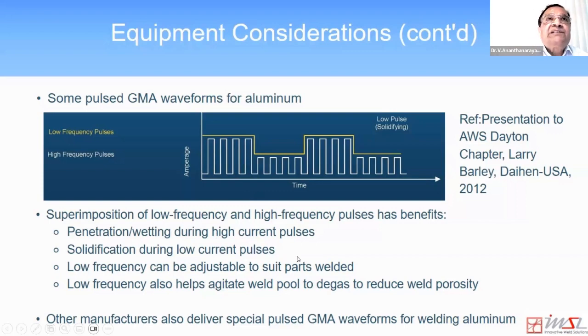One of the reasons is that aluminum is a very conducting metal. And if you keep welding at a current that melts the initial start of the weld, by the time you travel a certain distance, the weld and the metal get too hot. And there is a need to cycle low and high currents like this to maintain a constant weld width. And you can adjust the duration of these depending on your part material thickness combination and joint geometry to get an acceptable weld bead that has uniform wetting and penetration along the length.